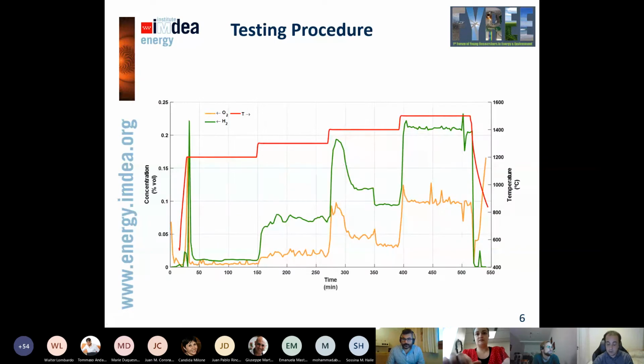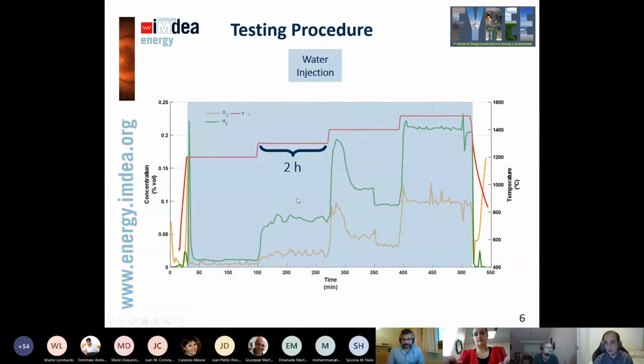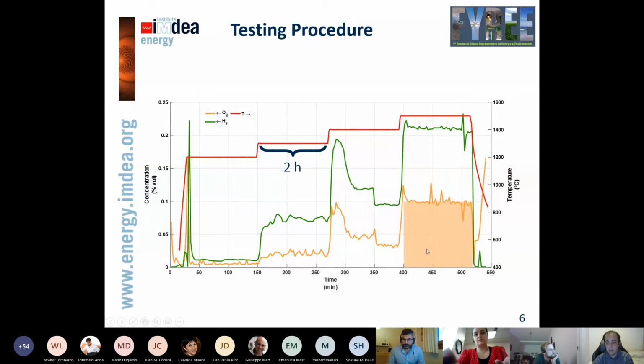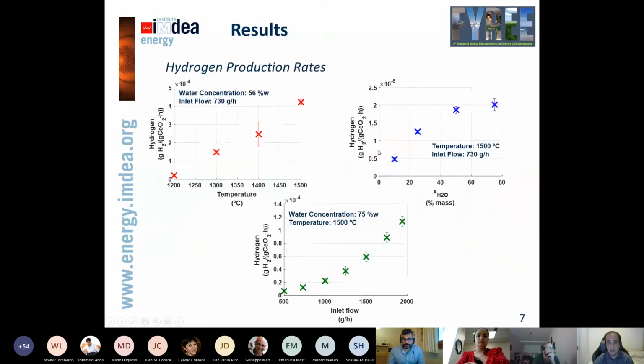Well, this is the plot of the first test, the temperature test we ran. This is raw data basically, and what we did was just increase the temperature step by step on our requirement, and stay there for 2 hours. We kept the water injection on during all the test once we reached our first set point, and afterwards, to treat those data, we did the integration and normalized the results depending on the real time and the actual ceria mass inside of our bed. Obviously for oxygen and hydrogen. So now we can start moving on to the results.